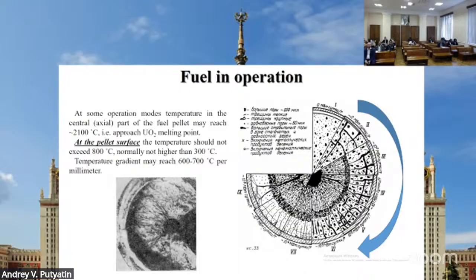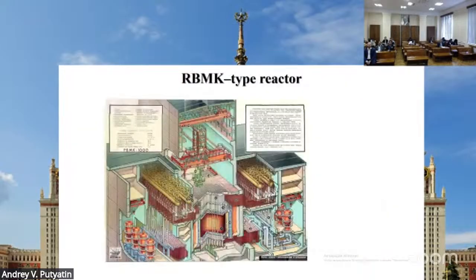And in the end, you end up with the so-called high burn-up structure. So the grain size of the uranium fuel changes dramatically. You have a very strong gradient in fission and activation products like plutonium, which is very heterogeneously distributed along the pellet. But nevertheless, what is important is that the fuel structure changes a lot during the operation.